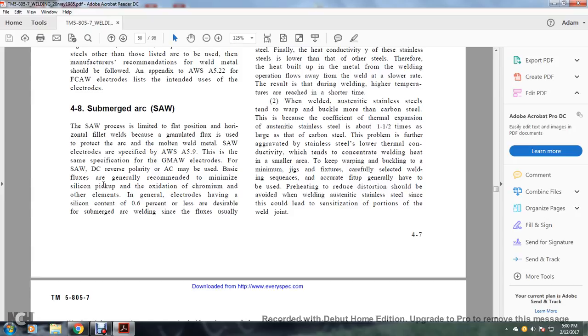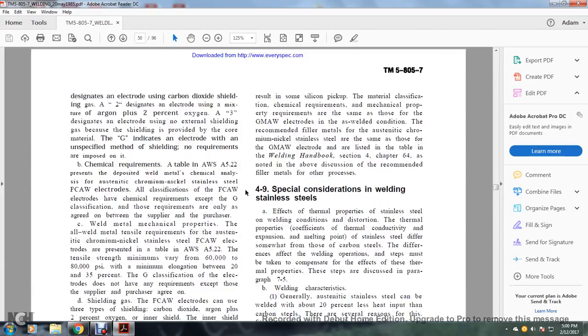flux is generally recommended to minimize silicon pickup and the oxidation of chromium and other elements. Electrodes having a silicon content of 0.6% or less are desirable for submerged arc welding. Fluxes usually result in some silicon pickup. Material classification, chemical composition, and mechanical property requirements are the same as those for gas metal arc welding electrodes, as well as the weld condition.